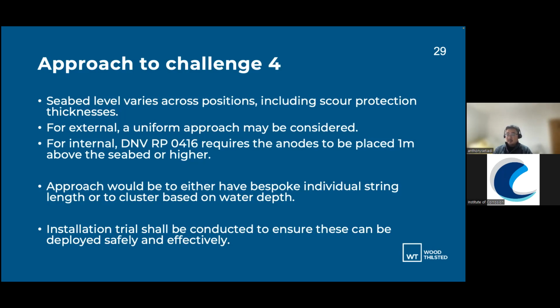But obviously, to do that, you need to make sure that the bottom anode and the top anode are bound by the upper level and the lower level. In this case, the lower level is the seabed level. The seabed level can go between, let's say, 30 meters up to 20 meters, which means there's a 10-meter variation. So when you put the anodes down, you cannot just put a 20-meter string, because then how would that protect a 30-meter? It doesn't. So what we try to do is to go 1 meter above the seabed level, and that's the bottom anode, where it can then help to protect the uppermost buried zone as well as the bottom of the water.